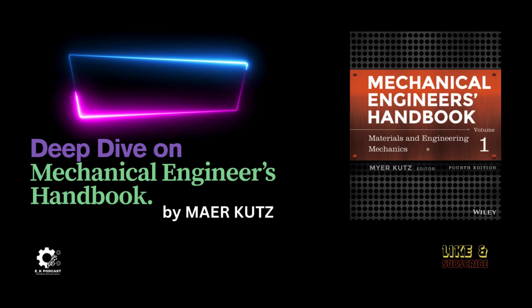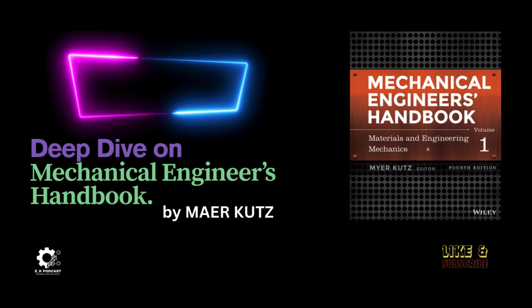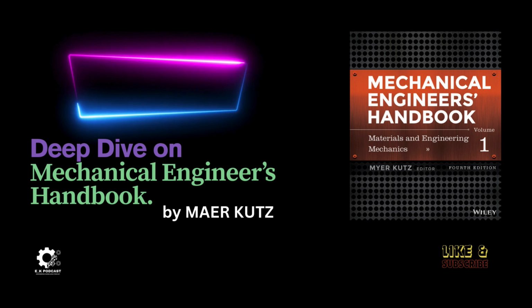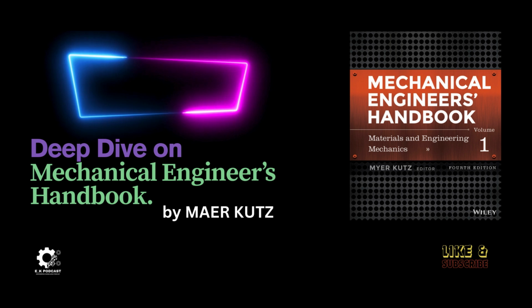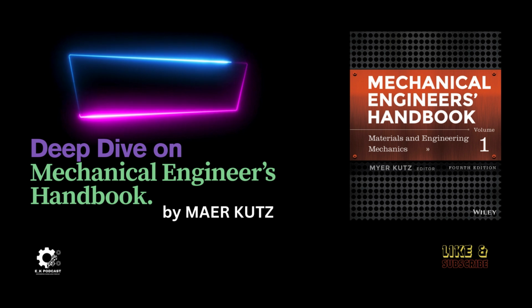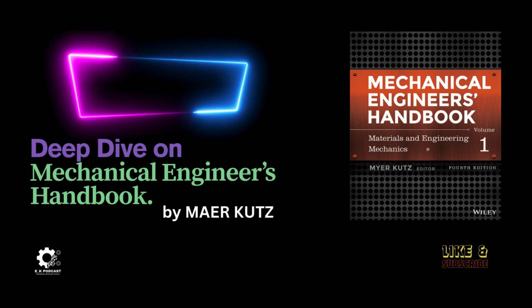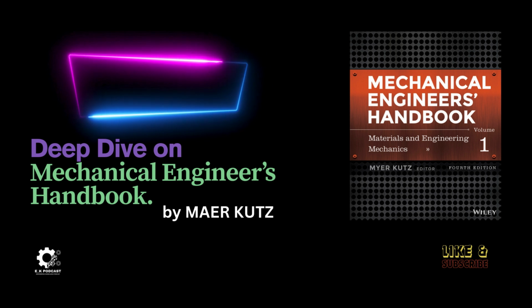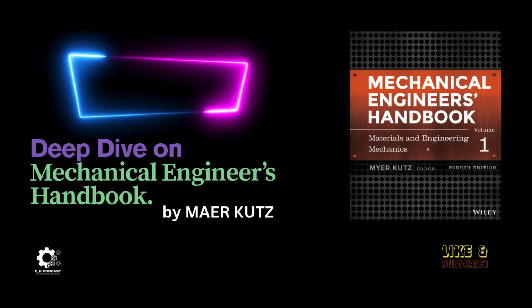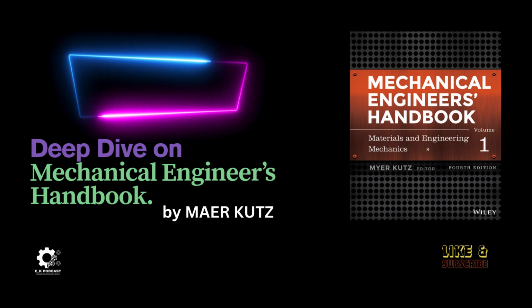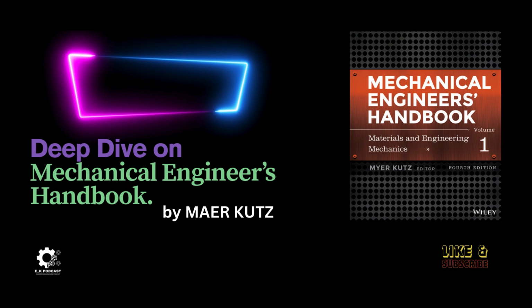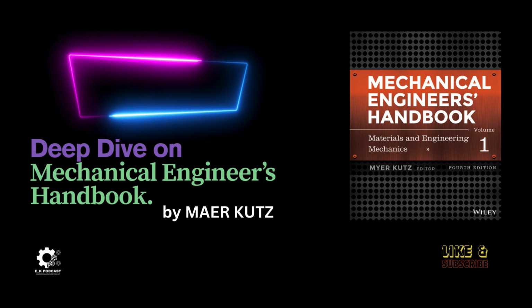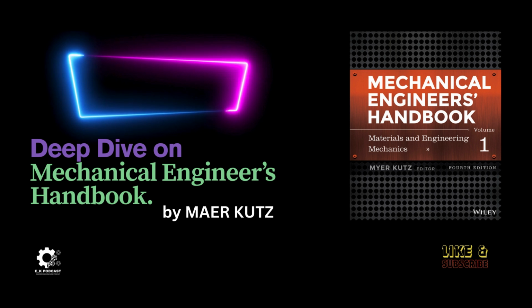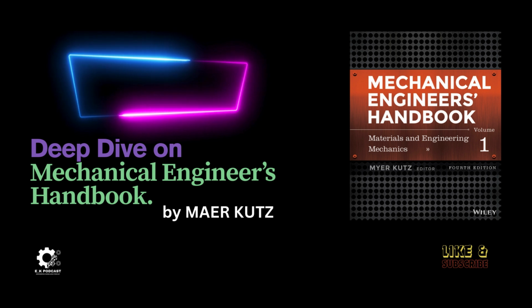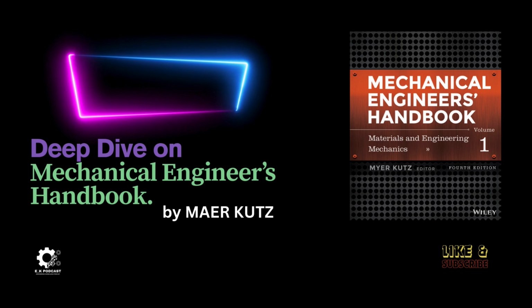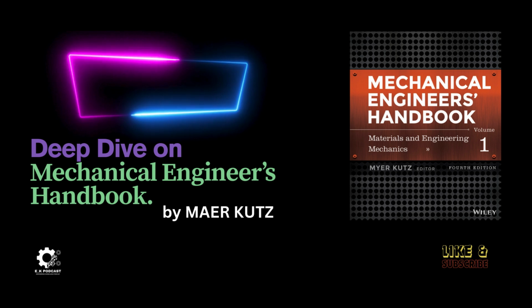Yeah. What about welding stainless steel? Is that pretty straightforward? For the most part, yeah. But with austenitic stainless steels, the main challenge when welding is this tendency to develop cracks as the weld cools down. They call it hot tearing. Hot tearing, got it. Now, for grades with, let's say, less nickel, around 15% or less, you can actually adjust the composition of the weld metal itself to create a little bit of something called ferrite, and that helps prevent the cracking. Okay. But for grades with higher nickel content, forming ferrite isn't really an option.